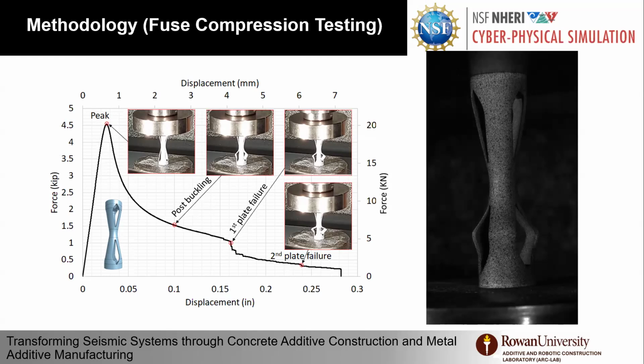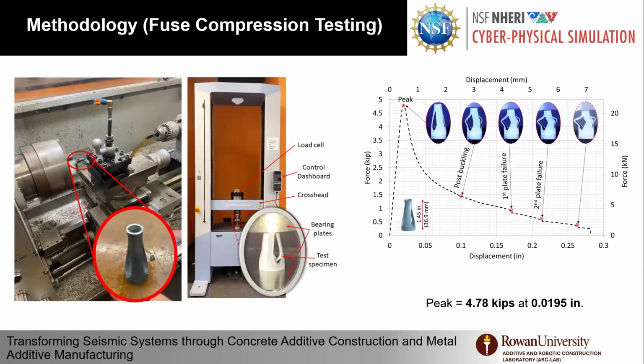And when we finished, we decided to machine the specimen, reclaim the undamaged part, and test it again to verify that the undamaged part is stronger. We tested that, and we achieved around 4,700, so it's around a 5 to 7% increase. This also translates to the quality of the printed option. You don't need to have one side much stronger than the other side, but you can have them fully synchronized, matching the strength.